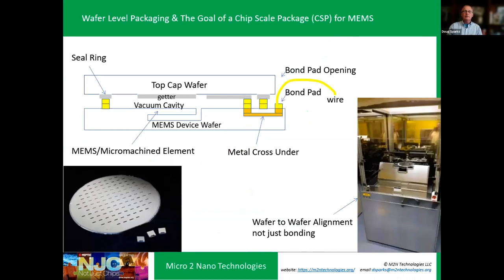Okay, now on to wafer level packaging. Wafer-to-wafer bonding is something I've worked with for years. Typically, you have a capping wafer, capping your MEMS or your micromachine device. You're going to have a seal ring, and again, this seal ring can be metal, it can be solder or eutectic, it can be glass, it can be an adhesive. You can do silicon direct bonding, you could do anodic silicon glass bonding. You've got to have cross-unders if you're going to use wire bonding. So think of that. You've got to get under that seal ring and keep the seal ring hermetic.